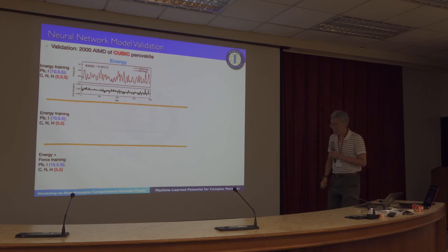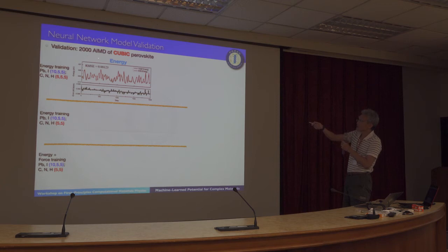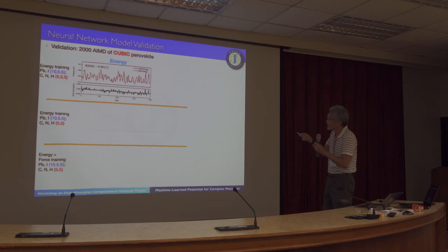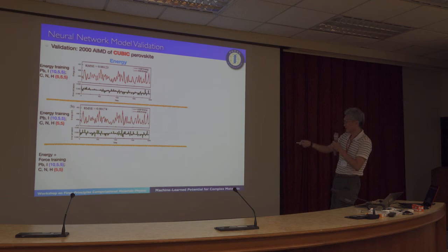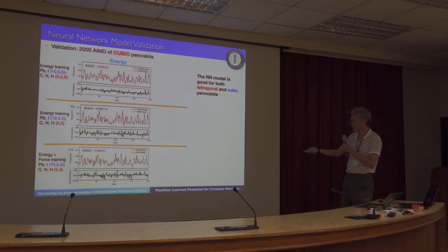And we also carry out additional validations because we happen to run into a very picky referee. The validation is that we run 2,000 steps of ab initio MD of cubic perovskite, and I need to stress once again, the training set was generated using the tetragonal perovskite. The black line is from VASP, and the red line is from the neural network potential model. You can find they almost coincide with each other. So this is for setting 1, and for setting 2, once again, they also overlap with each other very well. And the third one, there's still very good agreement.